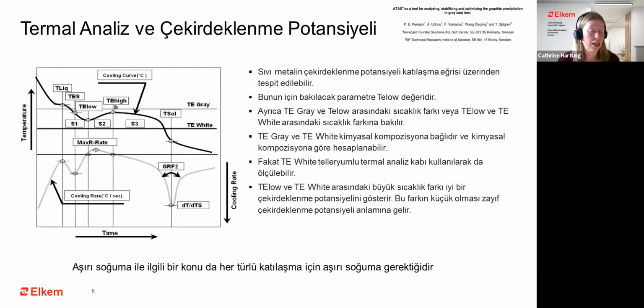And then we come to nucleation potential and thermal analysis. Now, thermal analysis can be used to read nucleation potential of a melt. I used a figure here from the article which is referred to in the top of this slide from Novacast. But thermal analysis is actually just a time temperature curve, as mentioned. And the different points in the curve have defined names and represent the solidification.